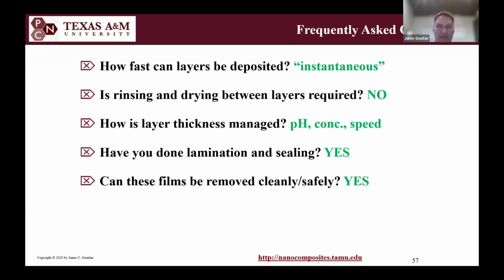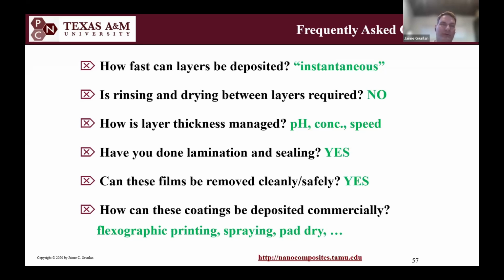Questions that people ask me, especially industrial people: how fast can the layers be deposited if I'm doing layer by layer assembly? I would say almost instantaneously. If you look in the literature, people do 1 minute, 10 minutes per layer, and it's totally unnecessary. Whatever is going to get deposited pretty much deposits immediately. You don't have to rinse and dry between layers. Of course, you'll make a more beautiful film if you do.